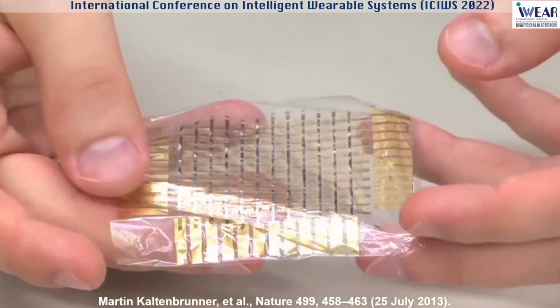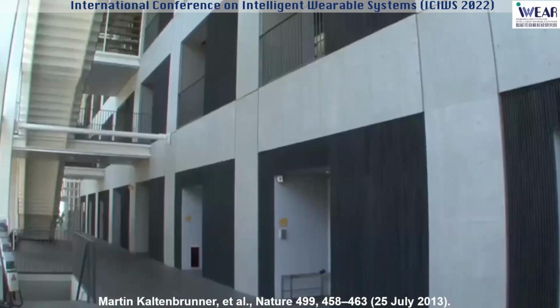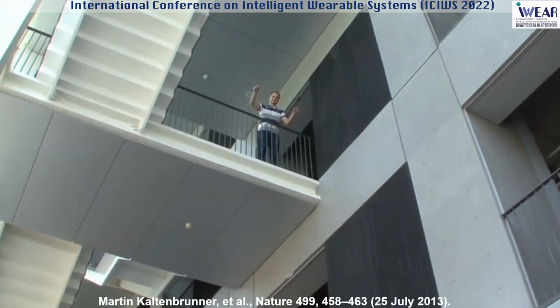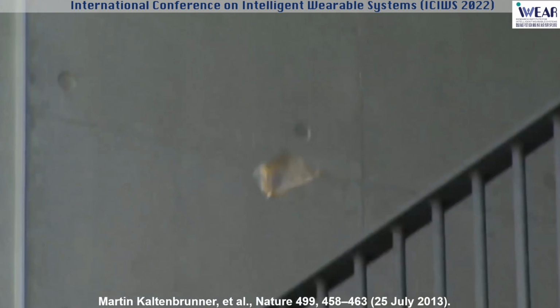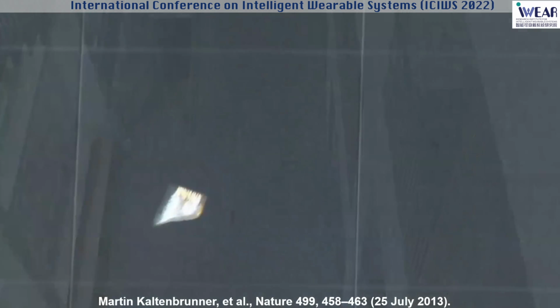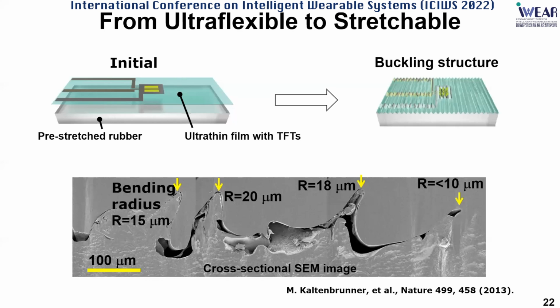And as we briefly mentioned, we are working on the organic electronics that's compatible with the solution process and suitable for the large area electronics. And we manufacture the organic thin film devices onto the plastic substrate with a thickness of 1 micron, which is floating in the air. And one of the benefits to utilize the ultrathin device was to transform the ultrathin film devices to be stretchable by using the wrinkling structure or accordion-like structure.